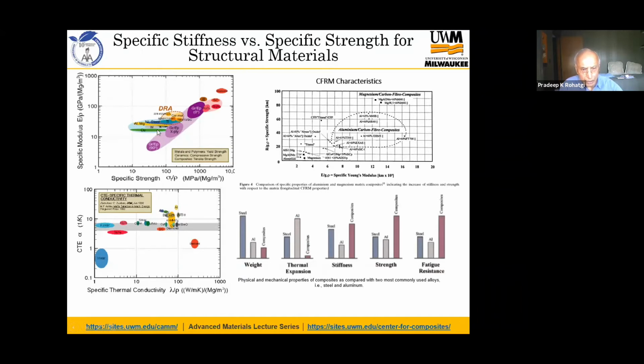Most of the monolithic metals that we use today, the aluminum and steels, they are here. As you add microparticles, you move along this direction. So now you can make the parts much lighter. And if you add nanoparticles, it moves even more along this direction. So you make parts much lighter compared to monolithic metals when you use composites. And that's the motivation for using these in transportation systems. This is another slide that shows how in the case of aluminum and magnesium, you have moved from monolithic to microcomposite and to nanocomposite, moving along this diagonal.